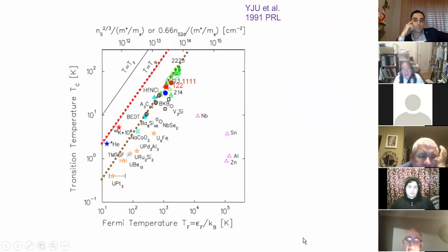And so these are very different features. Okay. And the next thing you can try by making this kind of plot is that there's another important phenomenon in solid state physics called Bose-Einstein condensation. All these super-something phenomena actually originate from various different types of Bose-Einstein condensation. So we essentially obtain the number of carriers divided by the mass. And we can assume that these carriers are essentially fermion particles, but then you can pair each fermions and assume that the pairing occurs at very, very high temperature. So the system is just forming a gas of bosons, these paired objects or preformed pairs. And then you can ask, what would be this Bose condensation temperature? And this red dotted line is that hypothetical idealized Bose gas condensation temperature.